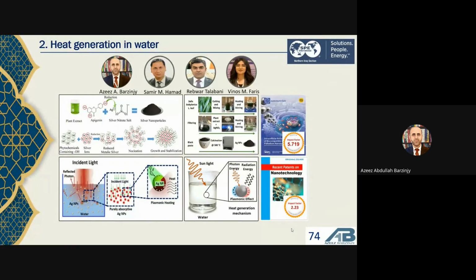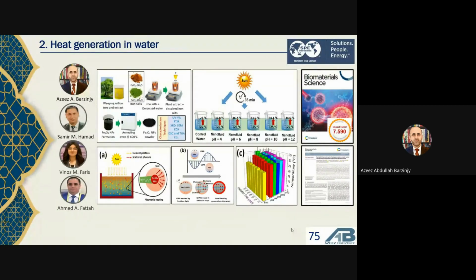And then later we could enhance this project by utilizing different types of nanoparticles. First we started with silver nanoparticles, then we utilized magnetite nanoparticles and zinc oxide nanoparticles, in order to find the effect of the type and size of the nanoparticles on this heat generation inside water. So you can see this is the best we did, about 35 minutes. The temperature changed from 25 degrees Celsius to 34.6 degrees Celsius.